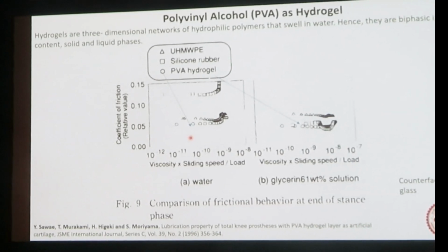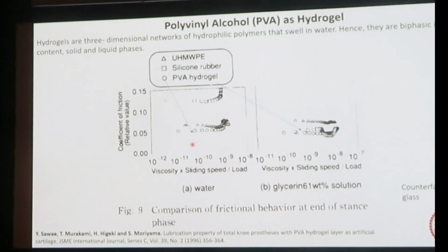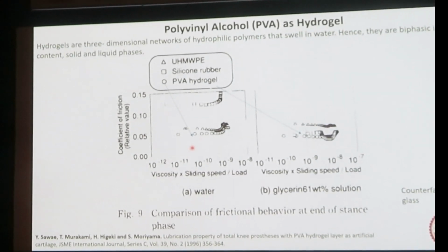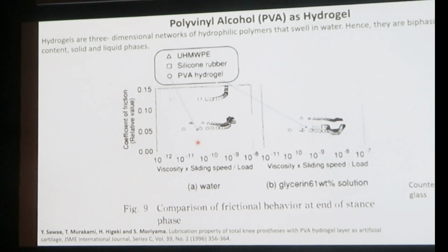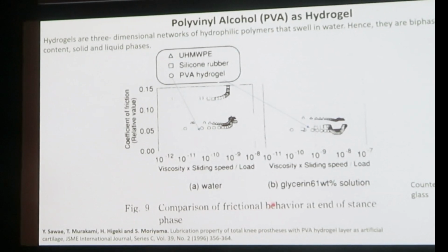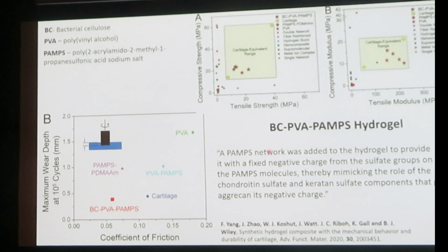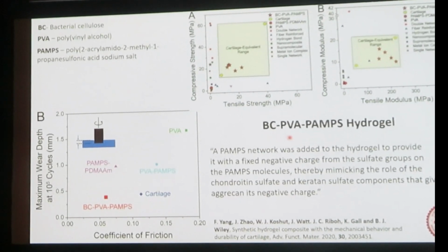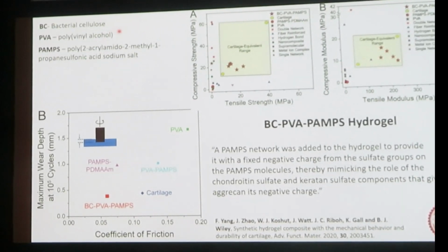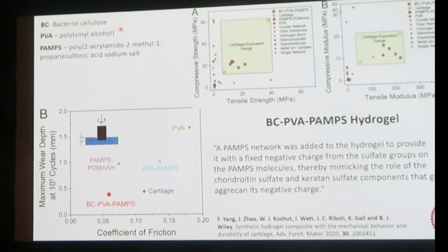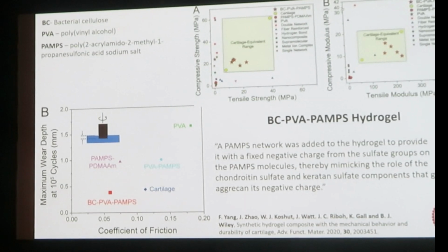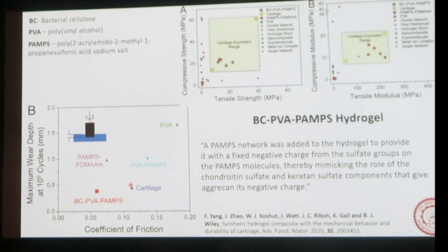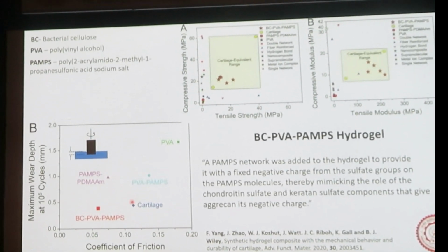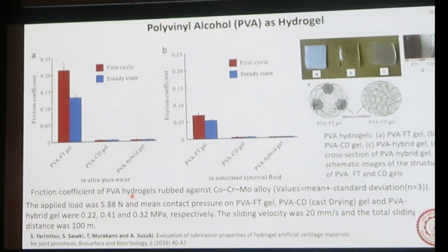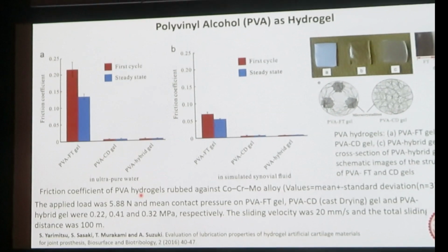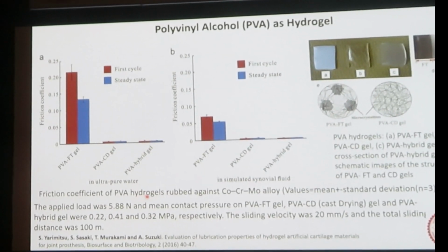Hydrogel is very, very popular, but still it is very hard to find any work where hydrogel wear has been tested. We can see a lot of friction related results, but hardly any wear results. This is a very old paper now, and here also friction results have been published. In another type of hydrogel, bacterial cellulose was added to increase the strength. The idea is that if you increase the strength, you will have better wear resistance, and they did find that there is some improvement. So perhaps hydrogel mixed with some sort of natural fiber might be a solution in the future, but again it has to be tried.